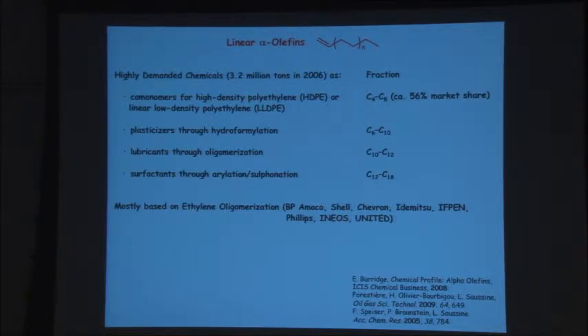Now, in view of this information and the growing demand for C4 to C8 fractions, the so-called short chain alpha olefins, remember we want to do oligomerization. We don't want to make polyethylene, which would be very long chain. We want shorter chains, in particular C4, C6. You need to have a catalyst which is selective for these.